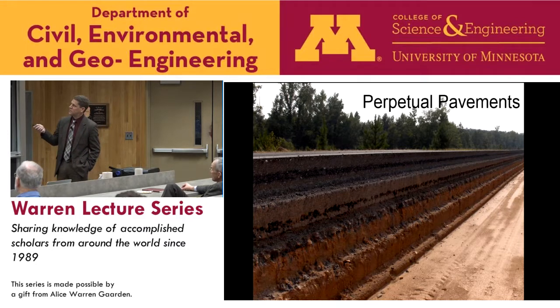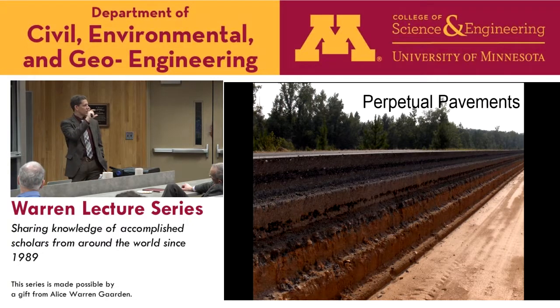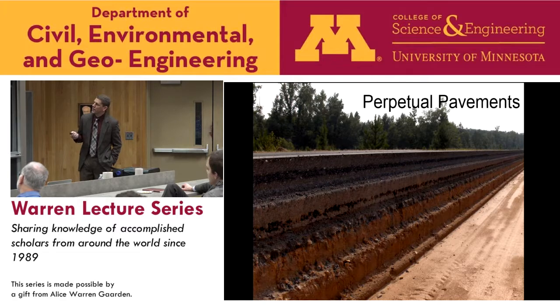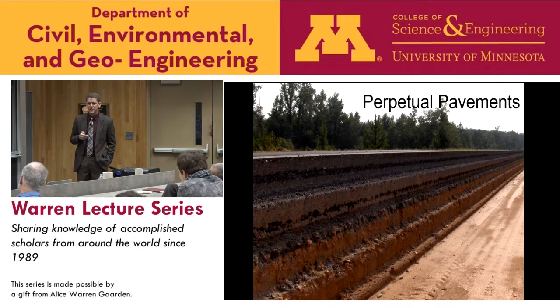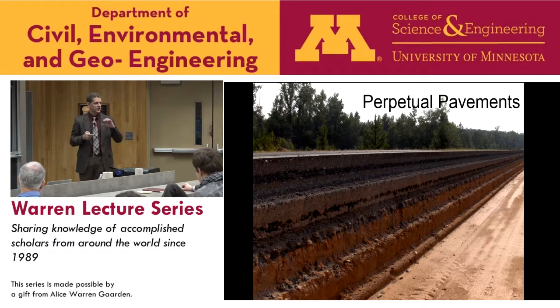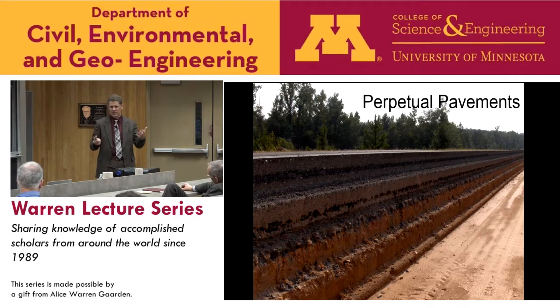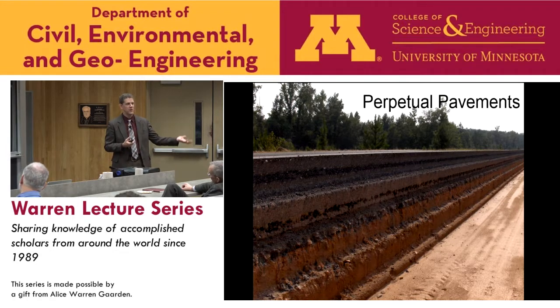So the idea is to build it thick enough, and this is really over thick. This was a cross-section at our test track that was purposely built very thick. This is about 30 inches of asphalt here. And we were looking at just the performance of the top few inches. But the idea is to try to build it just thick enough that you wind up with only distresses at the very top of the pavement that we can mill and inlay, and again, that's the most cost-effective, most sustainable option. We can even take the material that we've milled up, reconstitute it, and put it back down. It's 100% recyclable. So that's, again, a very sustainable option.